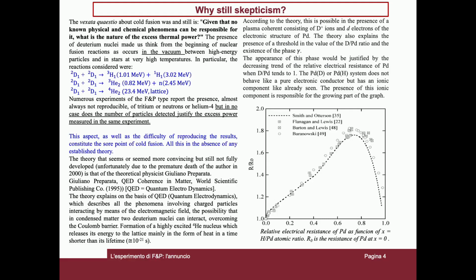According to the theory, this is possible in the presence of a coherent plasma made up of deuterium ions and electrons of the electronic structure of palladium. The theory also explains the presence of a threshold in the value of the deuterium-palladium ratio and the existence of the gamma phase. The appearance of this phase would be justified by the decreasing trend of the relative electric resistance of palladium when the deuterium-palladium ratio tends to 1. The palladium-deuterium or palladium-hydrogen system does not behave like a pure electronic conductor, but has an ionic component, as we have already seen. The presence of these ionic components is responsible for the growing part of the graph.